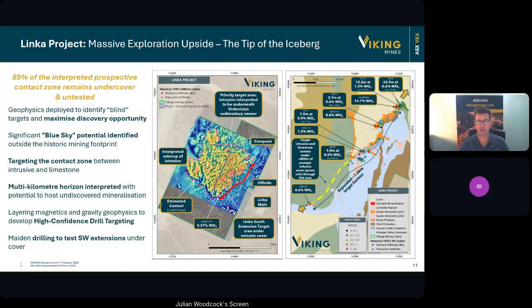Now, just stepping out and looking at the scale of the opportunity, and this is really key important to share through this webinar. The map on the right-hand side shows Conquest and Linka, and this is the surface expression in the area that was extensive mining, which is about 800 meters long. At the start of the presentation, I referred to the surface sample in the southwest, 0.6%. That sits under this green unit, which is that volcanic cover, which is not mineralized, which overlays the historical, or so the older mineralized rocks, and believe that extends the mineralized target horizon to 1.6 kilometers.